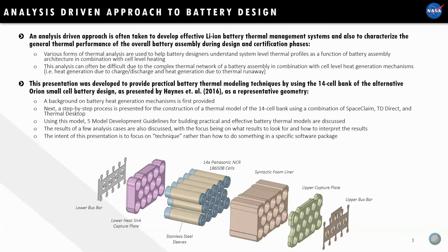So this is a good question, right? When a cell explodes, all of those materials inside of the cell start reacting, there's a level of pressure buildup and expansion, and then the materials squeeze out. And so you can have a drastic effect on the theoretical thermal conductivity, right? Of course, when you look at the literature out there on what your interface resistance is between the jelly roll and that cell casing, it's for a cell that's just sitting there, right? It's not necessarily possible to make that measurement. And so the short answer is no. We did not take into consideration the gap forming between the case and the jelly roll, although that would make for an interesting study.